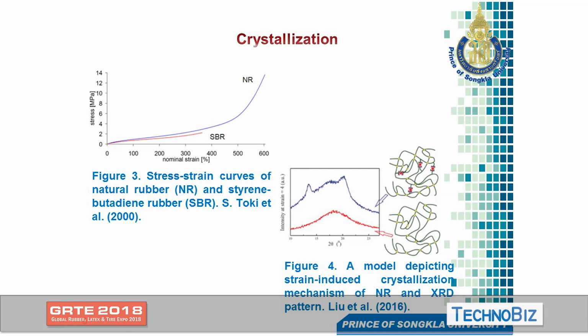Comparing natural rubber with synthetic rubbers, natural rubber shows strain-induced crystallization. At lower strain or lower deformation, nothing happens. It's just like SBR or synthetic rubbers. Once we apply a high stretching or higher deformation, the stress sharply upturns and increases, meaning that strain-induced crystallization occurred in natural rubber. We can observe the strain-induced crystallization by looking at the stress-strain curve.